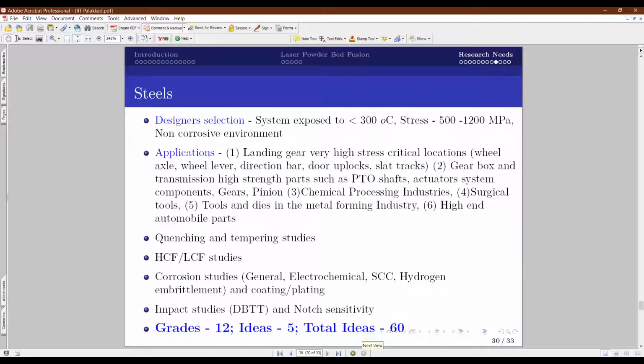And all the gear, landing gear parts are subjected to both low cycle and high cycle fatigue. So getting the fatigue data on these alloys is very, very important. Here you have to fix the material, you have to fix the heat treatment, you should have a clear understanding about the phases, then you conduct the property characterization. Otherwise the data will have a huge scattering.